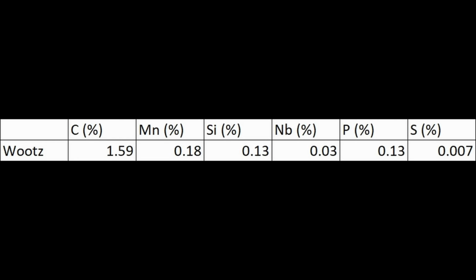We also measured about 0.13% phosphorus and 0.13% silicon. That likely comes from the pig iron. Pig iron can be high in silicates, those are silicon oxides, and it also has other impurities in it like phosphorus. So that is likely where those impurities come from. Luckily, phosphorus is pretty common in ancient blades when they have measured the composition of them. So overall, apart from the niobium addition, this Wootz looks very similar to ancient Wootz, and I think it'll be a good steel to test and compare to modern steels.